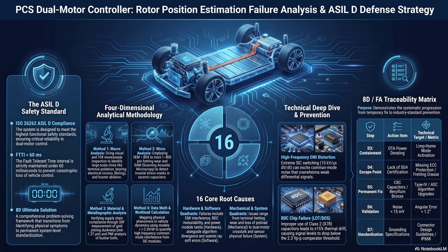But uncontrolled generation is the true hardware killer here, right? It absolutely is. In field-oriented control, or FOC, the algorithm mathematically transforms the 3-phase currents into a flux-producing vector, the d-axis, and the torque-producing vector, the q-axis. Okay, so if the angle estimation suddenly skips 180 degrees due to a severe resolver glitch, the FOC algorithm's reference frame is entirely inverted. It fundamentally believes the rotor is facing the exact opposite direction. So it mathematically reverses the q-axis current. Instead of applying positive thrust, the inverter commands maximum negative torque. And because the vehicle possesses immense forward kinetic energy, the motor is forcibly back-driven. It transitions instantly from a motor into a massive, unregulated generator. It's aggressively pumping kinetic energy back into the high-voltage DC bus.